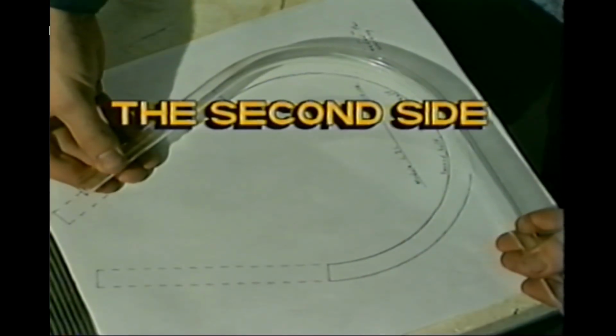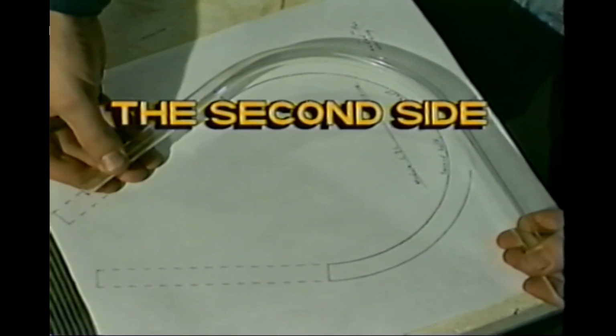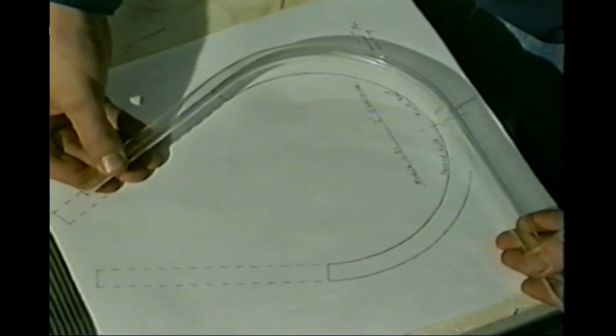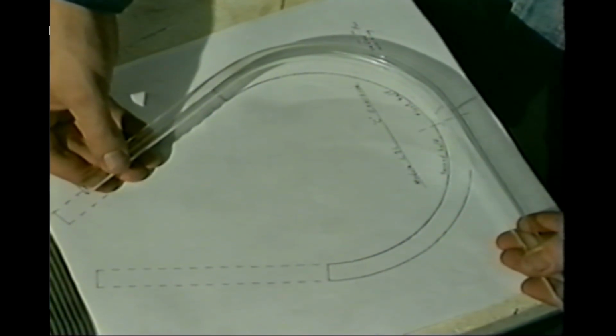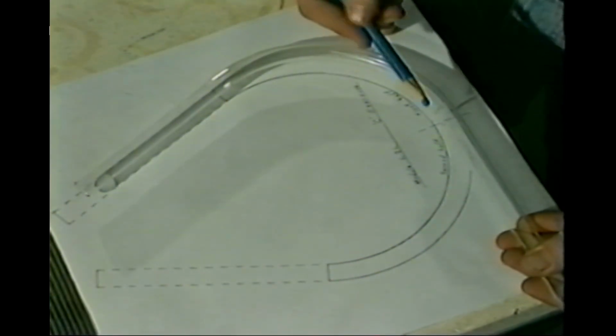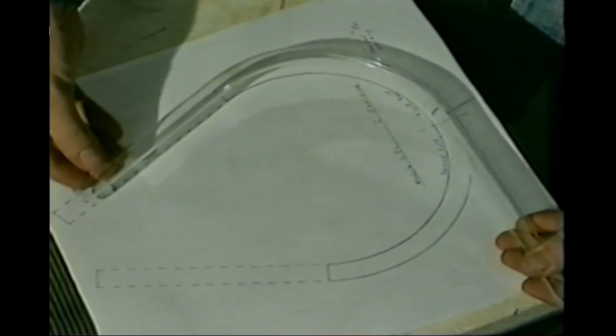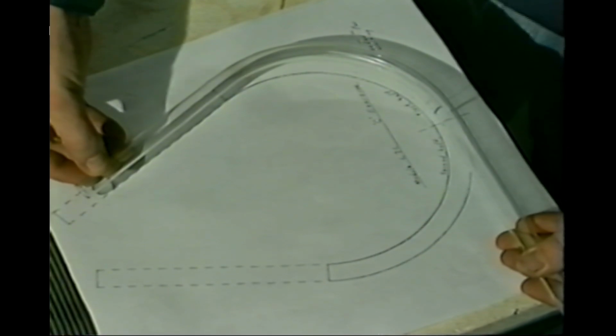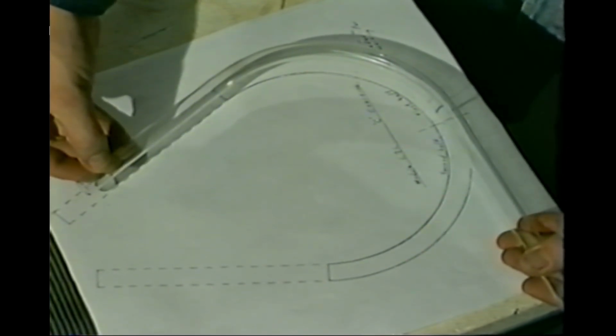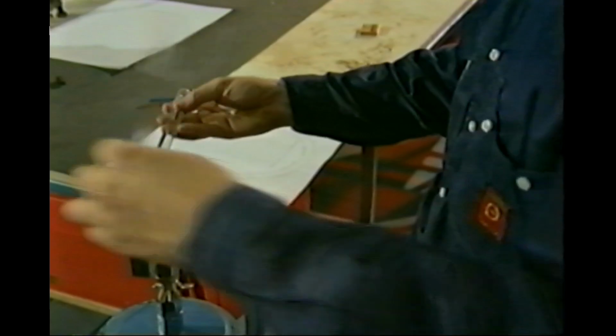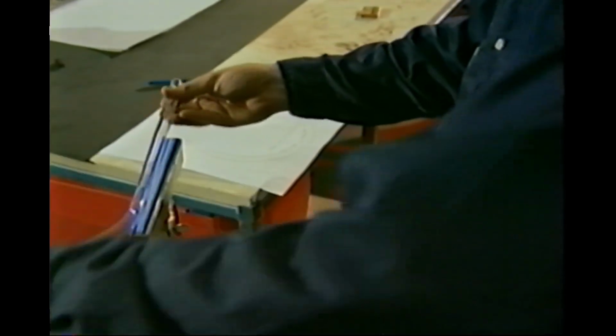The second side of the C curve is more difficult to achieve and requires a slightly different method of bending. For the second side, lay the cold curve on the drawing, making sure the first side fits. Remark the center of the glass length, and this time marking the melt mark 10 millimeters to the right of the center mark, so that the melting overlaps into the curve slightly to aid continuity of bending. Place the melt area in the flame with the left hand holding the curve and the right hand holding the straight length. Melt this time by rotating the glass back and forth fully, allowing the glass to heat up the same amount as the first side.